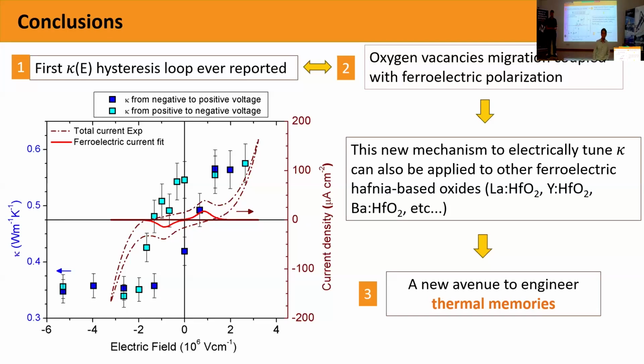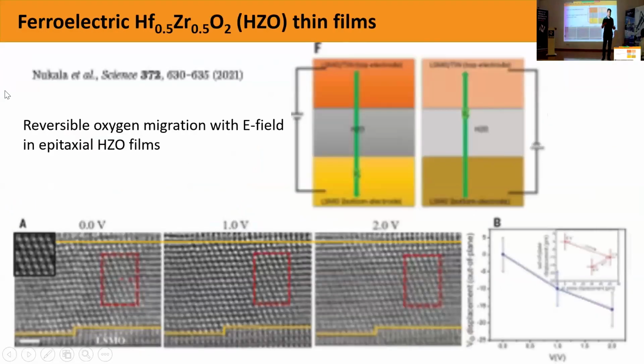I was wondering if you have any experimental proof for the presence of those vacancies. That's a very nice question. Actually, we couldn't see them. We wanted to see them with scanning transmission electron microscopy, but the vacancy concentration, if you could show the backup slide, the number of vacancies is so low, about 3 vacancies per 100 unit cells is sufficient to reproduce the results in the theoretical calculations.